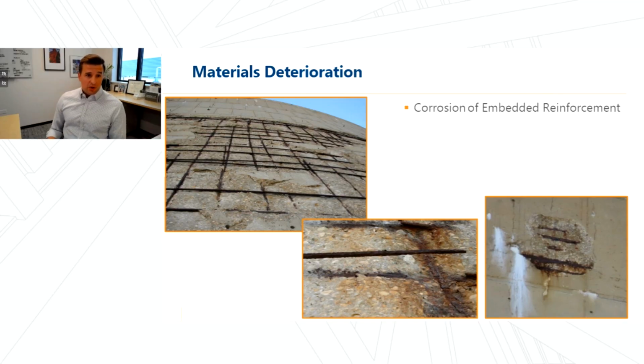So when metals corrode, they expand. And when embedded reinforcement corrodes, this expanding steel can cause tensile stresses on the concrete. So concrete is very strong at compression. It's relatively weak in tension. And so these expansive tensile stresses can cause cracking and distress to the concrete. It can reduce the gross section of the concrete and the concrete element. And it can also reduce the effectiveness of the embedded reinforcement through reduction in steel area and loss of bond, like we see here in this bottom photo.